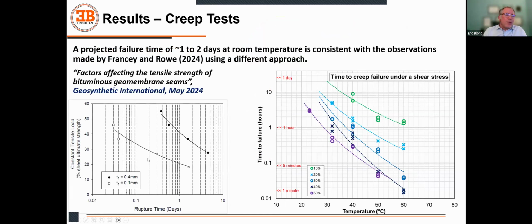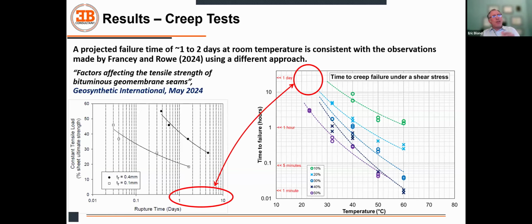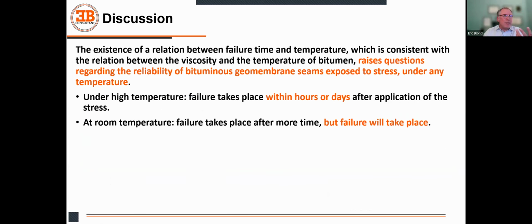And they published this graph, which is connecting the failure time with a percentage of the tensile strength. And it's funny to see that they are also observing failure times in days for a percentage of the shear strength, which is between 10 and 20%, say. And this is completely consistent with what we have observed. So despite the fact that we did not use the same approach, we landed pretty much in the same ballpark. So that to me was very, very interesting in terms of reliability of our studies.